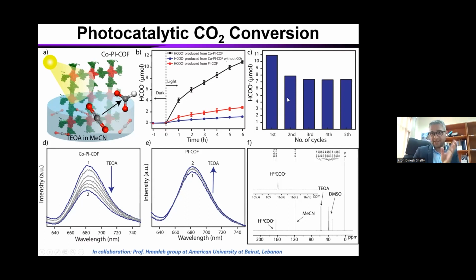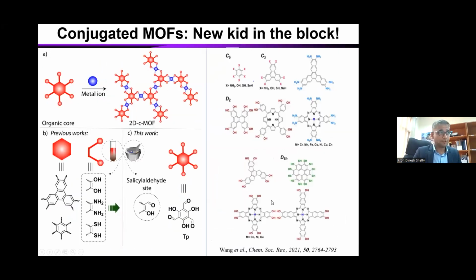Then we did a number of cycles. We have to see whether this catalyst can be reused. Then we tried to understand the mechanism, how it is happening, who is doing what. So in this case, the metal center is the cobalt, obviously. The light is absorbed by the conjugated donor-acceptor system. But when we talk about CO2 conversion, generally we have to confirm whether the formate is coming from CO2 or somewhere else. So generally people use the isotope labeling method. And we did that too, to confirm this is formate converted from the CO2 source.